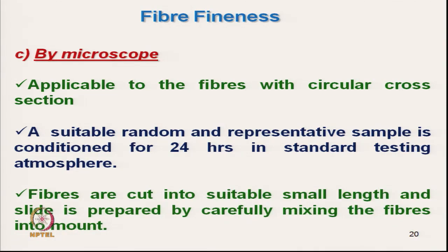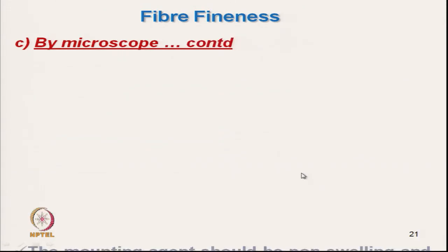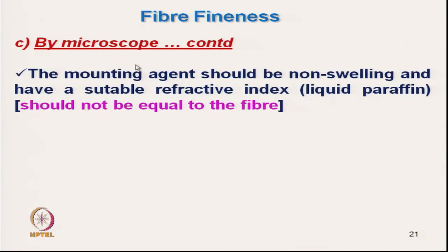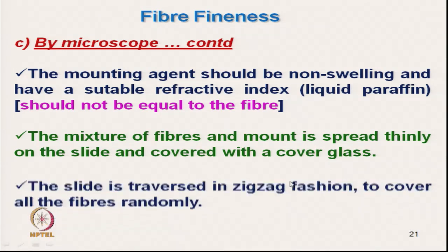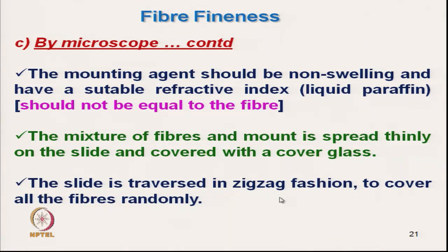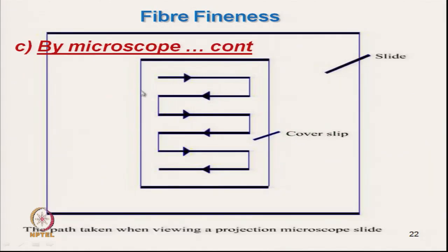we have to mix the fiber with the mount, and mix it properly and carefully. The mount is selected in such a fashion that it should not swell the fiber, and the refractive index of the mounting agent should be different from the fiber. Typically liquid paraffin is used, and the mixture of fiber and mount is spread properly on the slide and covered with the cover glass, and the slide is moved in zigzag fashion so as to cover most of the fibers randomly. So, this is the way the slides need to be moved.